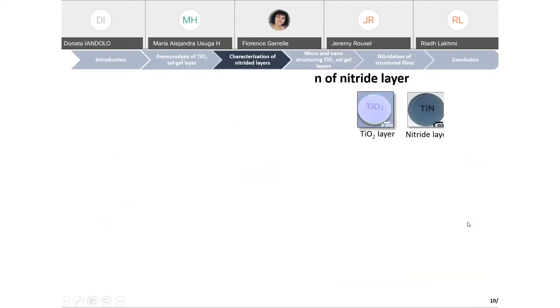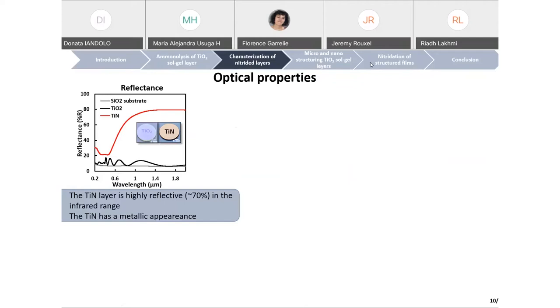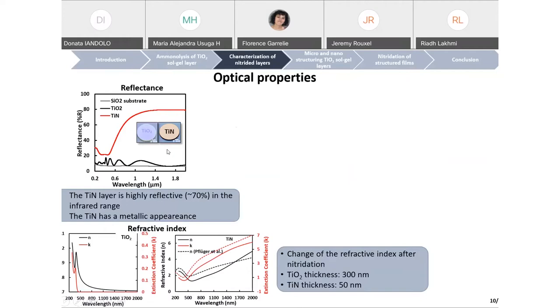For the optical properties, the reflectance, the titanium nitride layer is highly reflective, close to 70% in the infrared range. For the refractive index, we can see that it exhibits a change before and after nitridation. After nitridation, we can compare the refractive index with the values found in the literature. We can see that there is a little difference from the values found in the literature. It is due to the high porosity in the layer. Also, we can see that the titanium dioxide thickness is 300 nanometers, and after nitridation, the titanium nitride thickness is 50 nanometers. So, a high densification of the layer was carried out.